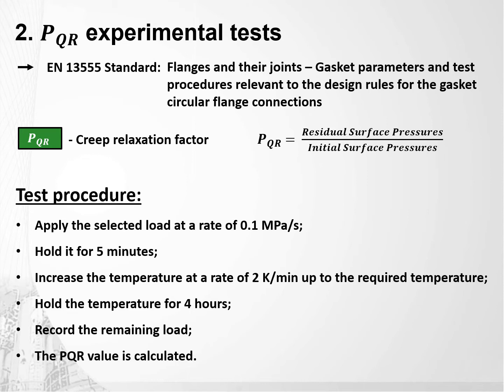The test procedure is quite simple. You apply the selected load at a specific rate, then you hold it for five minutes and increase the temperature at a specific rate to a required test value. You then hold the temperature for four hours and record the remaining load. The PQR is calculated as described earlier.